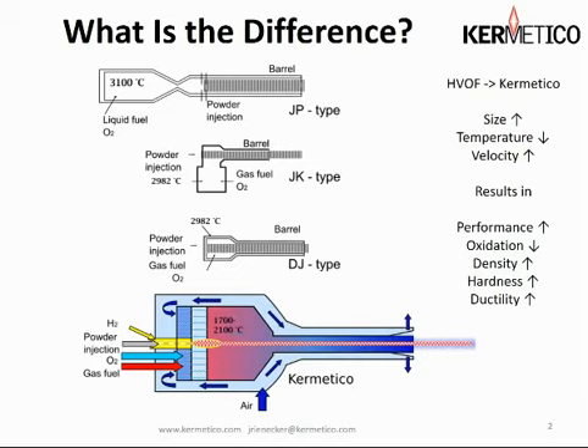This all results in very different characteristics for our coatings. First, a difference in our gun, as we pointed out, besides being in color, is that it's much larger. So in the combustion chamber, we have plenty of time. Because of the large diameter, velocity through here is relatively slow, so we have plenty of time to gently heat the feedstock material at a lower temperature than any of these other approaches.